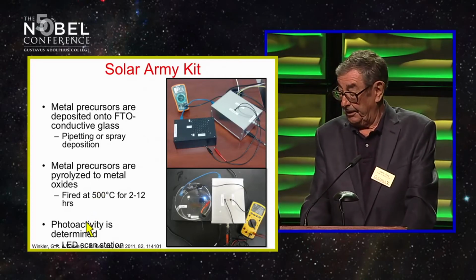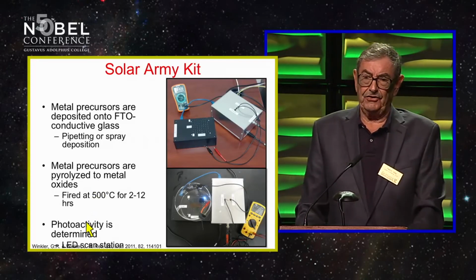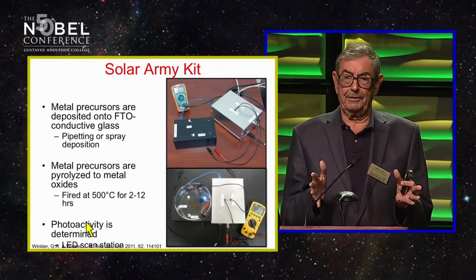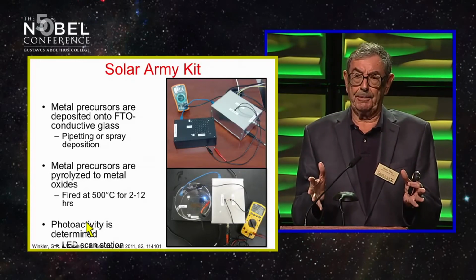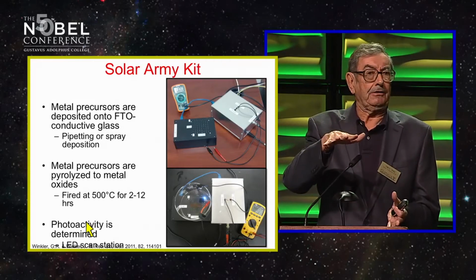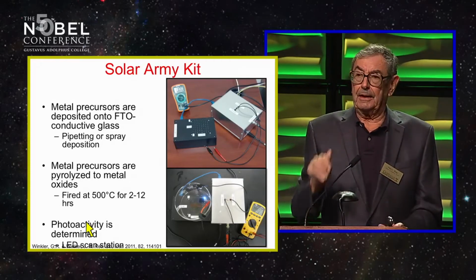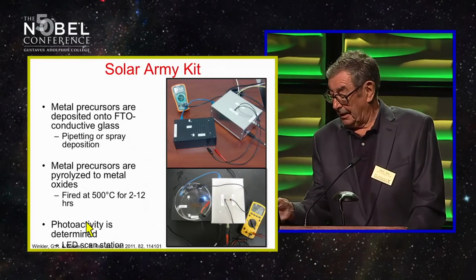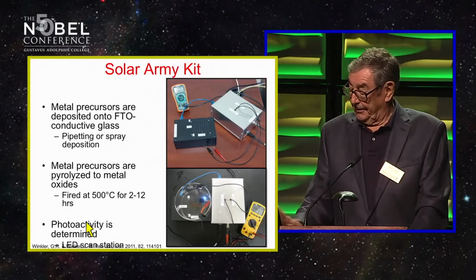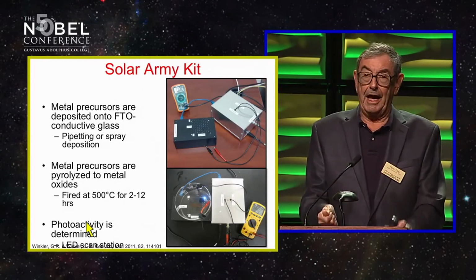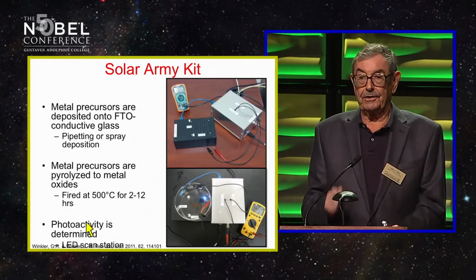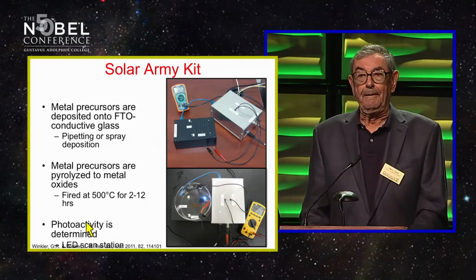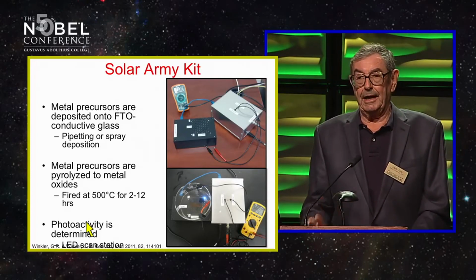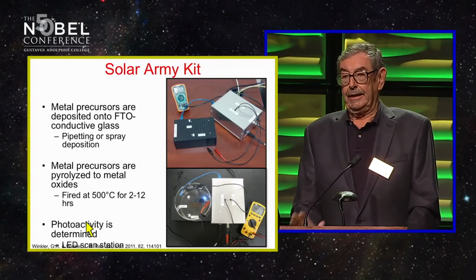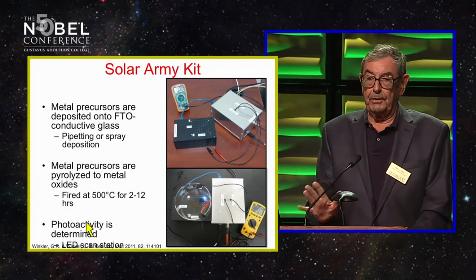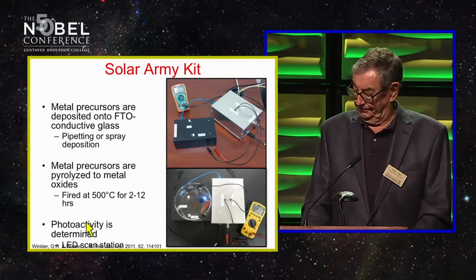Then you determine the photoactivity with an 8x8 LED scan station that we designed at Caltech and built at Caltech to supply to all of our brigades. So they can slap this 8x8 metal oxide plate onto the 8x8 scan station, turn on the lights, and the red and green and all the different colored lights come on. We have this hooked up to an electrochemical rig reading out current and voltage, and at certain current and voltage conditions, we are pretty sure we're splitting water.